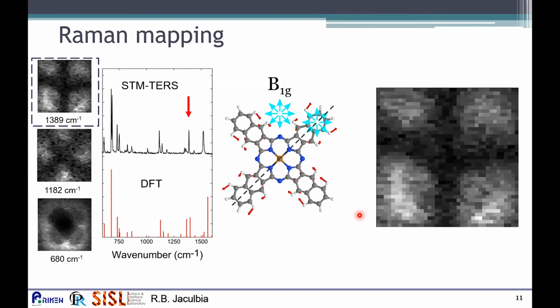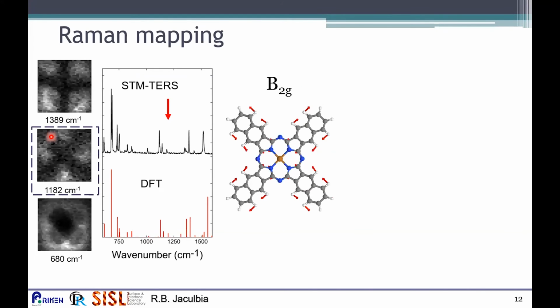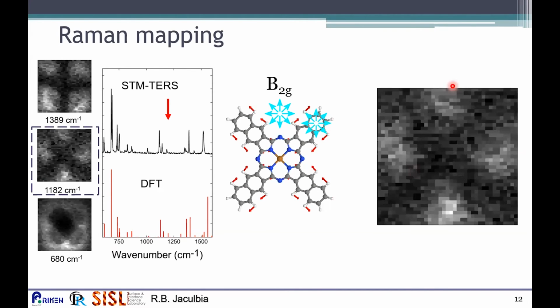On the other hand, for this mode, we found by comparing with DFT calculation that this is the B2G mode. This kind of mode has a symmetric axis along this axis, and considering that we put the tip around these positions here, at these positions the vibrations are in phase, while here the vibrations are out of phase. And then we can observe such a vibration wherein strong Raman signals are observed at the plus position.